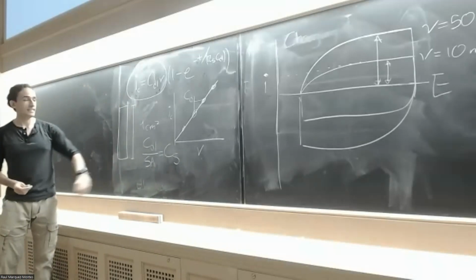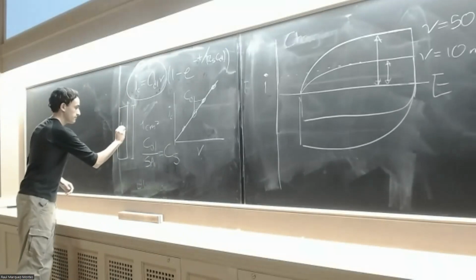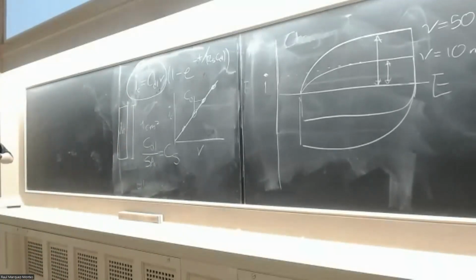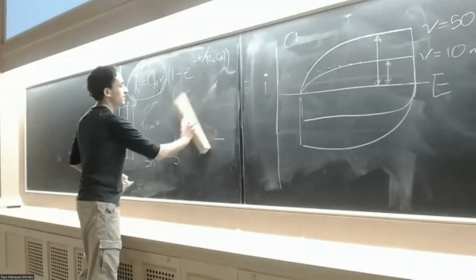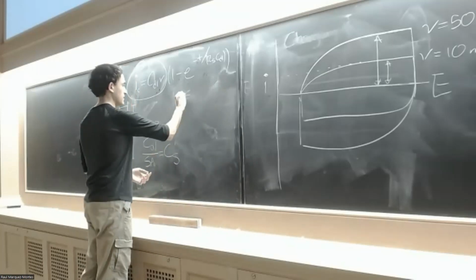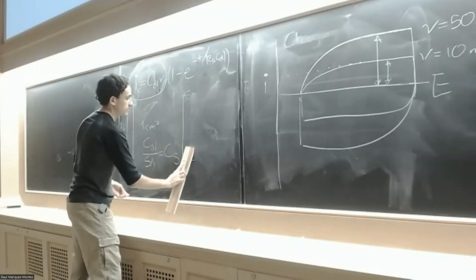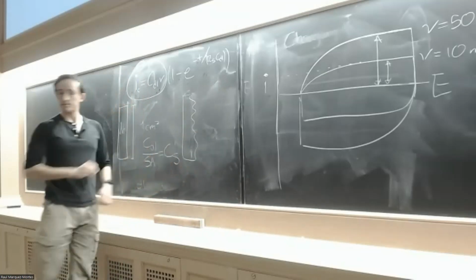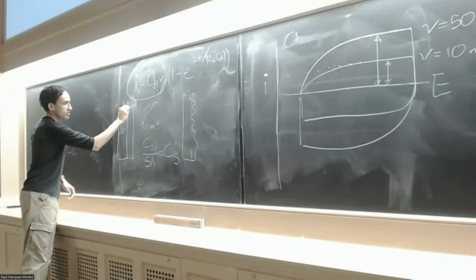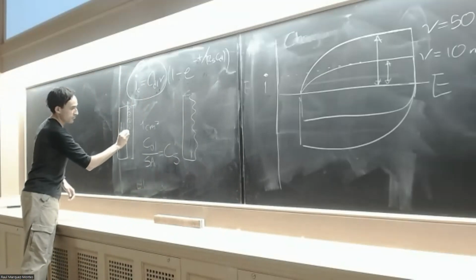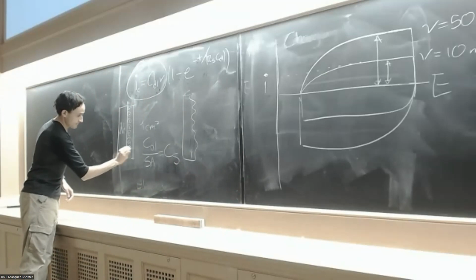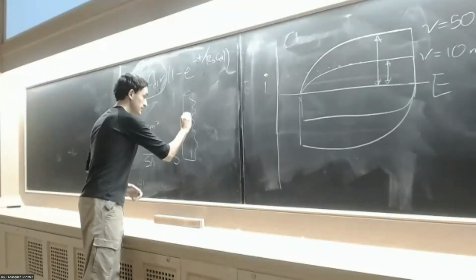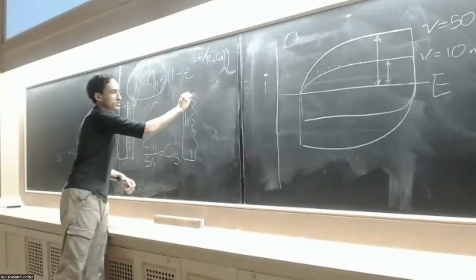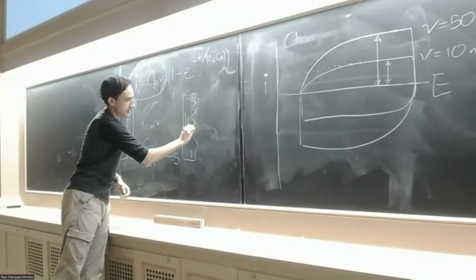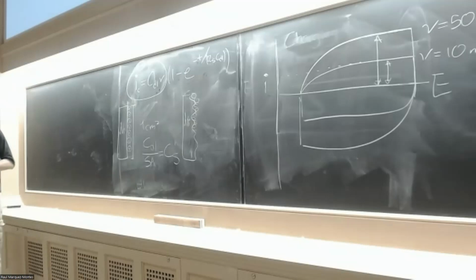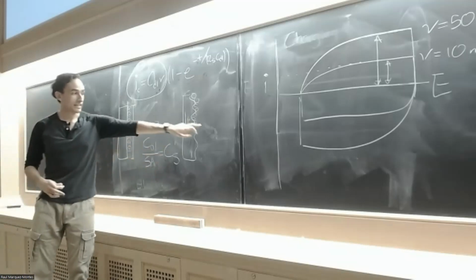The reason why this is helpful is that imagine this is nickel, just pristine nickel foil. But let's say that later you synthesize a rough material, so it's not smooth, maybe now it's something like that. We know that here all the charges build up perfectly flat on a smooth surface. But we're using the same material, nickel, so now there will be more charges like this. We're not changing the material. So that means that if we use this specific capacitance, we can get the surface area.